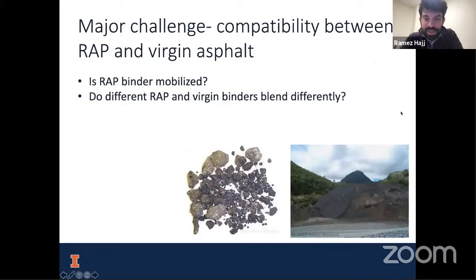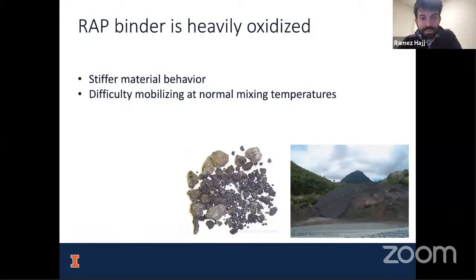However, there's still a lot of challenges associated with using RAP. The major challenge is the compatibility between RAP and virgin asphalt. When we heat the RAP material, we have to remember that this material is not like our virgin asphalt. This is a very stiff material. It's heavily oxidized, and it's difficult to mobilize and mix at normal temperatures.